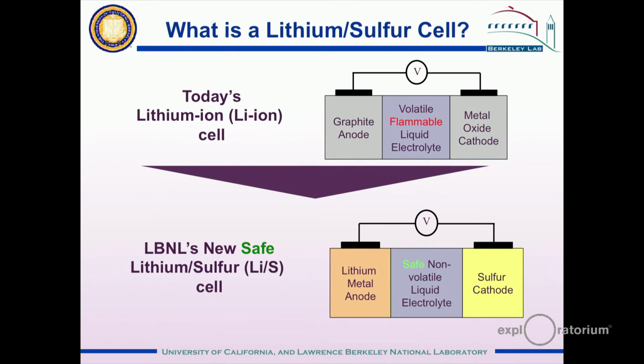In the positive electrode, we have a transition metal oxide like cobalt oxide or manganese oxide or nickel oxide. All of those are very heavy compared to the lithium. And these transition metal oxides just act as a host for the lithium. So during discharge, the lithium shuttles over to the transition metal oxide and is hosted there between the layers of the oxide material. And then when you recharge the battery, you move the lithium back to its original location in the negative electrode.